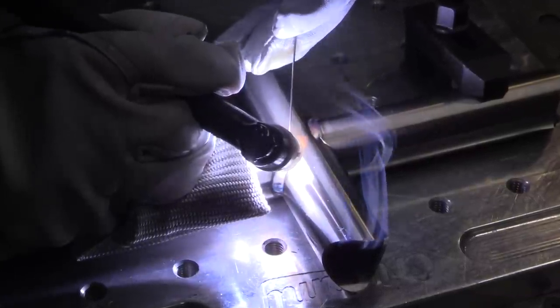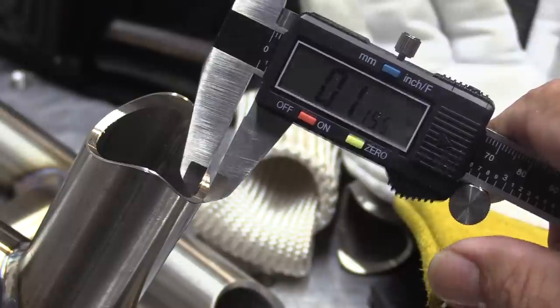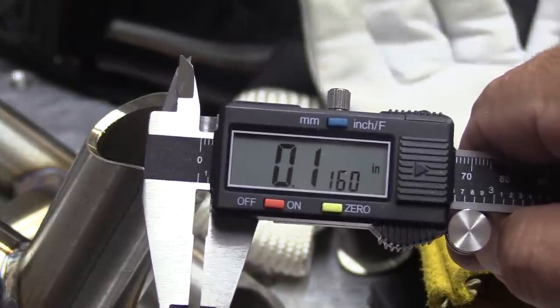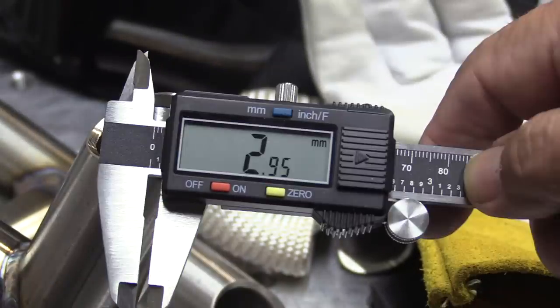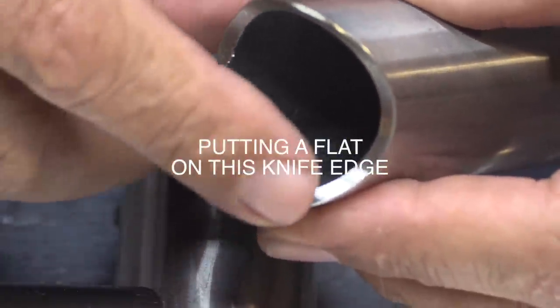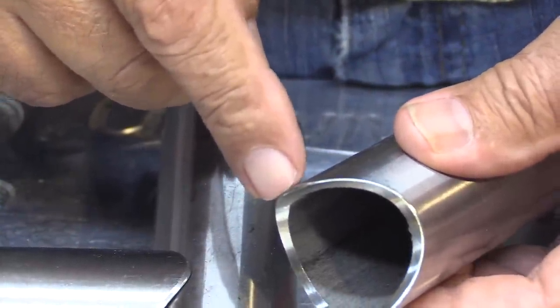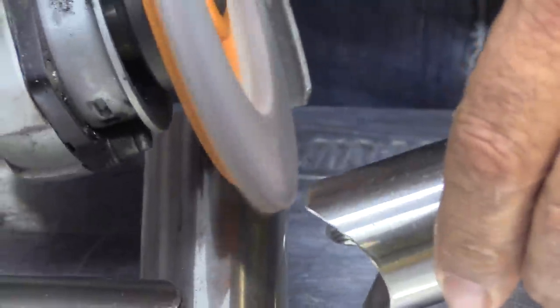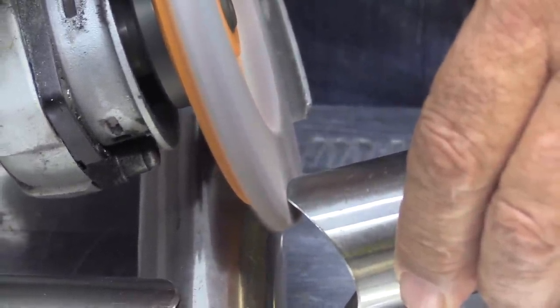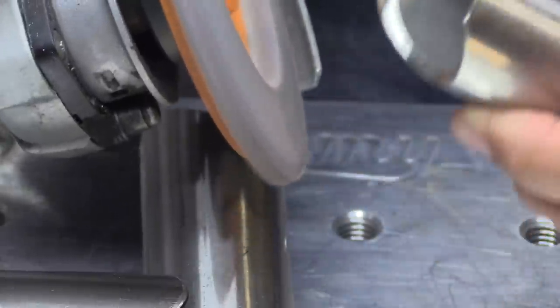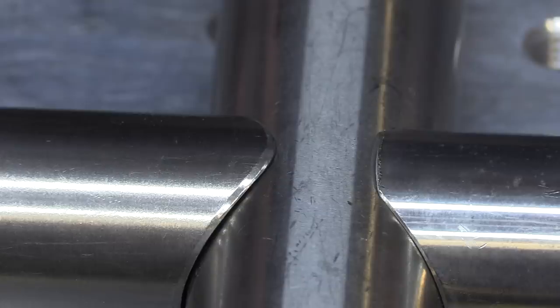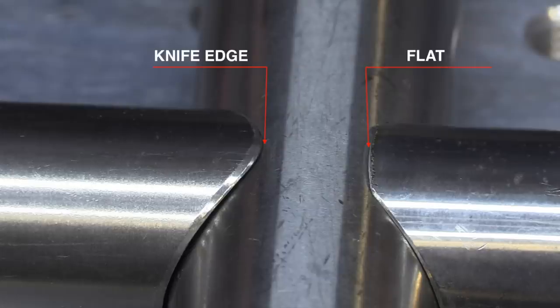Let's talk about several different things. They're roughly 120 wall thickness, slightly under 120, a little bit less than three millimeters. It's common to have a real sharp edge out here on this end, whether it was cut with a hole saw or however, and it's best to knock that down a little bit. It's hard to get a decent cross section thickness on a knife edge. So it's best to knock a little flat spot on it where you can get a nice little fusion tack in there and also a little bit of penetration without having a crowned up weld to do it.